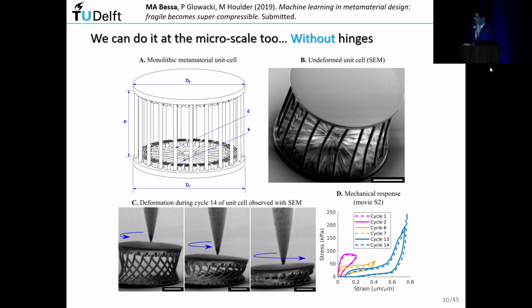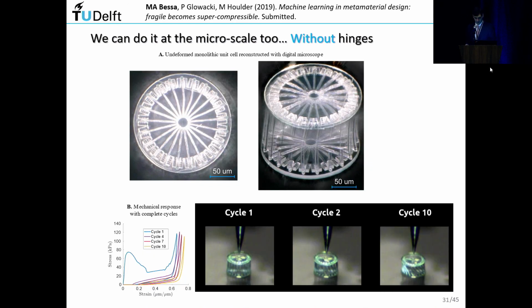And you can see here that this is how it looks like in the SEM. This is during the compression. This is what you have. So the dashed line is a second cycle that is exactly the same, and it's very reversible. It's exactly reversible. If you push the cell too much, then you start seeing that it's not fully reversible. There's some plasticity going on, but it's actually quite small.